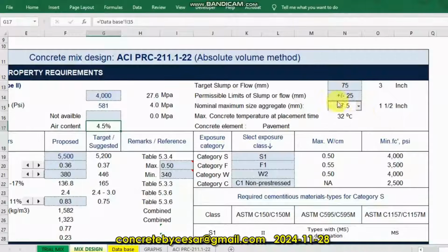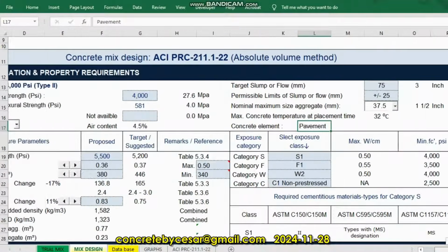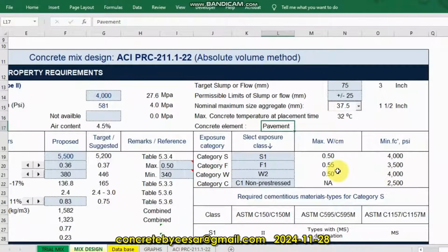Next, going to the right side of this template. The target slump will be 75 mm according to your specification, let's say, for example, which is equivalent to 3 inches. The permissible limits, let's say plus or minus 25 mm, with a nominal maximum size of aggregate, which is 37.5. You can choose from this drop down list. So let's say 37.5 in this example, or 1.5 inch. Maximum temperature 32, and let's say this is for the pavement concrete, the concrete element to be poured or cast.